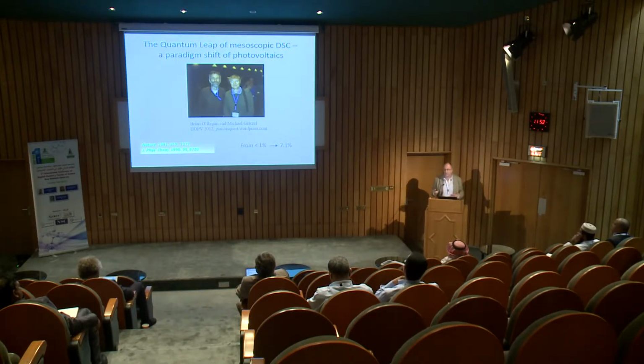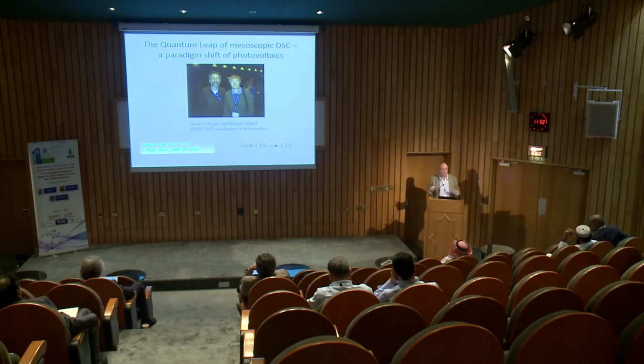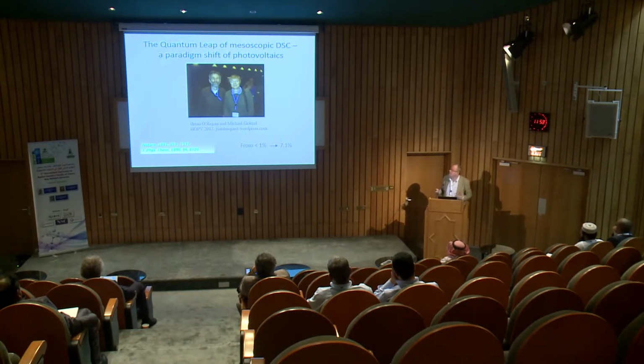and created a lot of interest, of course, for application, but also fundamentally because the solar cell they presented was based on a high surface area, nanoporous system, and according to textbook at the time, let's say now 1991, this was a way of how you should not make a solar cell. To use surfaces would, in principle, according to textbook, lead to losses, recombination losses. So this was very surprising, and even so that people didn't believe in it in the beginning.